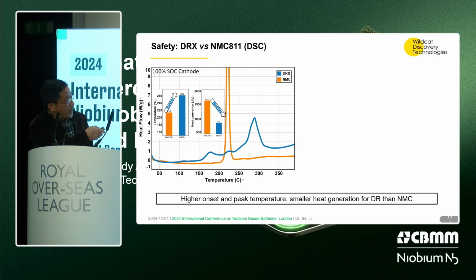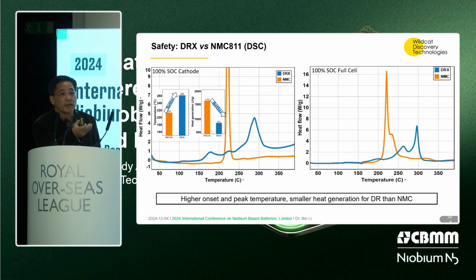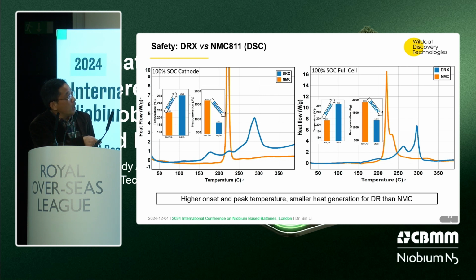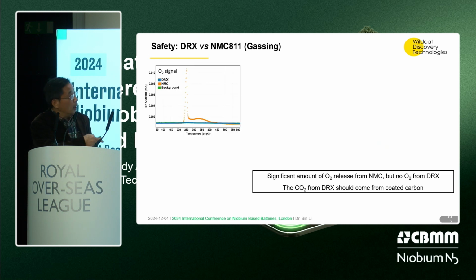And this is on the cathode, fully charged to 100%. And then what about the full cell? Here we do show the full cell. You have the cathode, anode, and electrolyte, and compare the difference between DRX and NMC. You still see the same trend, and also the much higher onset temperature of the DRX compared to the high nickel, and also much lower heat generation.